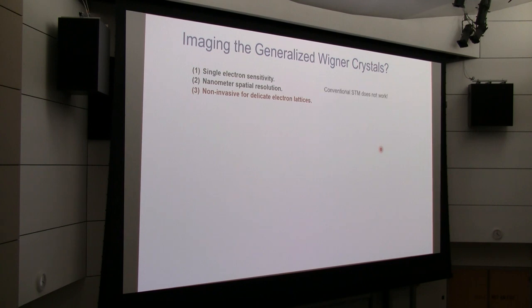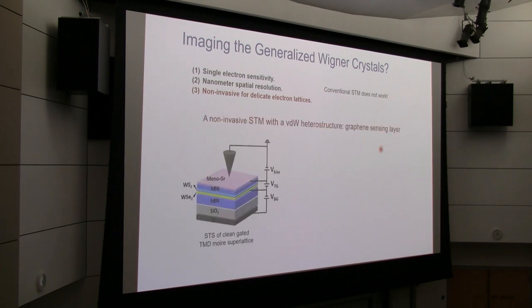So as a result, conventional STM doesn't work. The conventional STM has good enough sensitivity and spatial resolution, but when you bring a tip and try to do a tunneling measurement, you destroy this delicate Wigner crystal. So we came up with a modified technique where we combine the STM with the flexibility of engineering Van der Waals heterostructures.